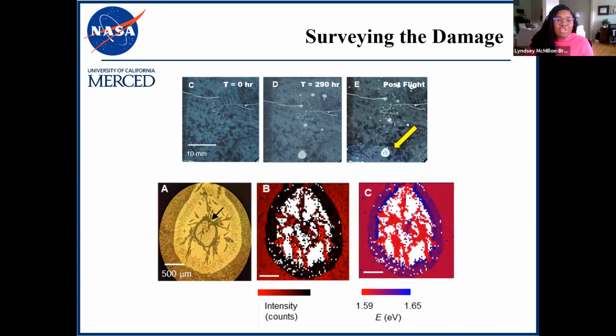So here we're going to take a closer look at the largest visible defect on the sample, which is shown on the top right in the post-flight image of the film. On the bottom left panel, we have a confocal image of that spot. And from here, we learned that this isn't just a hole in the film. In our lab, we were calling it the hole for a while because we didn't think anything would be there. It's not a hole, but there are actually some perovskite crystallite structures within that region.